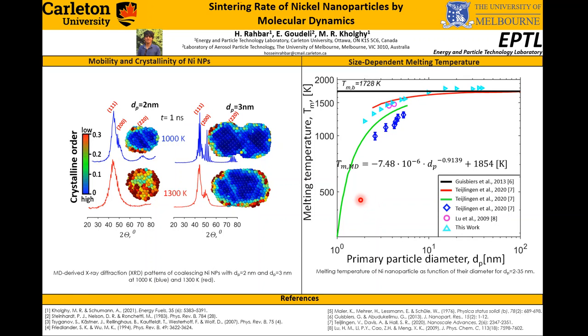The size dependency of melting temperature of nickel nanoparticle is investigated by calculating the average interatomic potential energy. The MD-derived melting temperature are compared with empirical models shown in green and red solid line, also available experimental data, the blue diamonds, and MD simulation results, the pink circles. The results are in a very good agreement with the literature. As we can see, by increasing the size of particle, the melting temperature increases and gradually reaches a plateau corresponding to the melting temperature of bulk nickel.